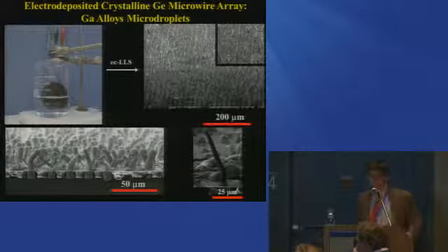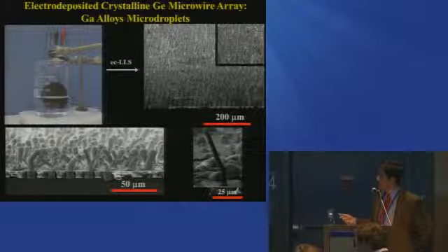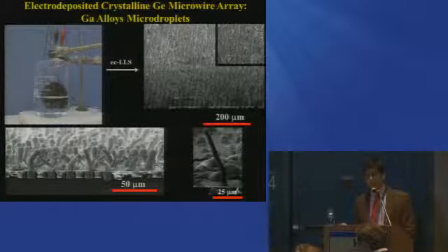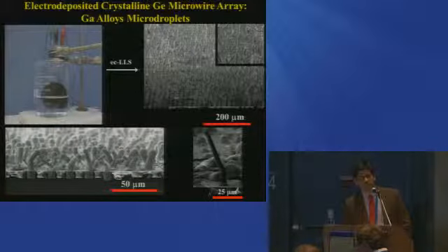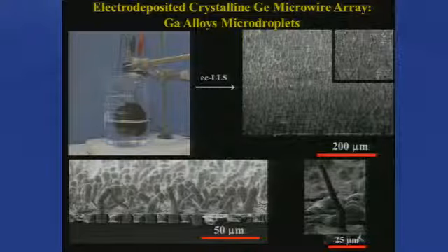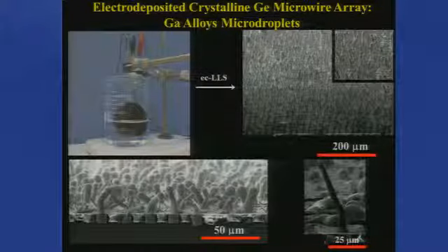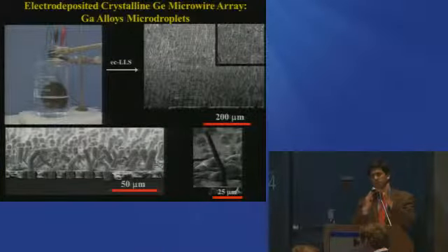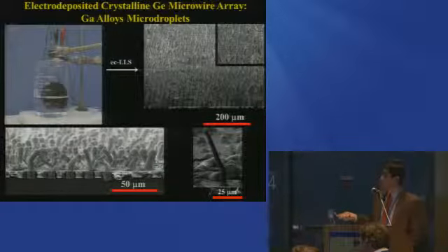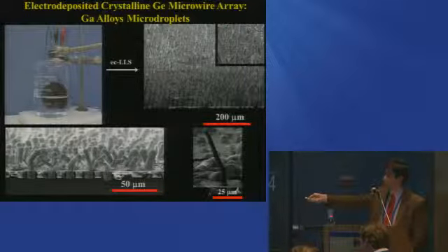And our answer has really been to move beyond using liquid gallium. We're interested in basically using alloys, or for lack of a better term, solders, to do electrochemistry. So if you think about using gallium-based solders, you can electrodeposit, again, through this scheme. You can deposit arrays of crystalline nano and even microwires. Here is a film now that's grown with a gallium alloy. These wires are much larger because the properties of the alloys have changed. And the interesting thing here is that these materials now have a much tighter aspect ratio, or they can be much longer, and if you didn't know any better, could be the equivalent of materials produced by a high temperature process. But again, we're producing it with that.